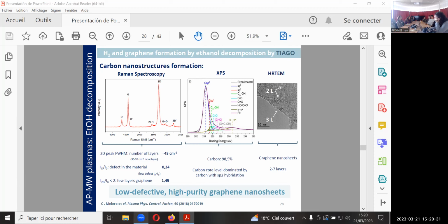So it's again coming to the idea of remains from graphite, that the graphene would come from the graphite. Having dominant sp2 is something strange, because you would expect that if graphene is newly formed from the gas phase, you would have a mixture of sp2 and sp3. Why do you end up with graphene made mostly from sp2? And it's clearly dominantly sp2 from the Raman spectra. So well crystallized. Yeah, something that needs to be explored. Yeah, you're right. It's so different from all the graphene made under different conditions. So for me it really indicates that the precursor is graphite. It's not the acetylene.